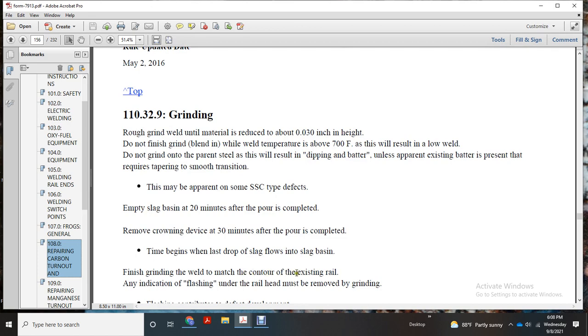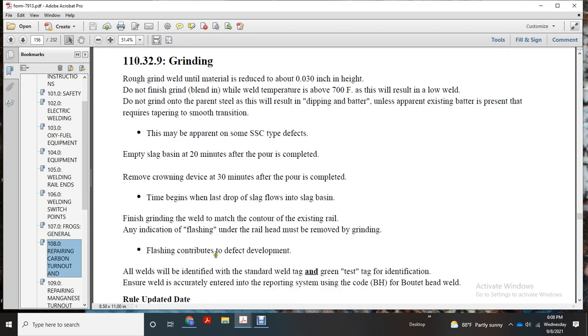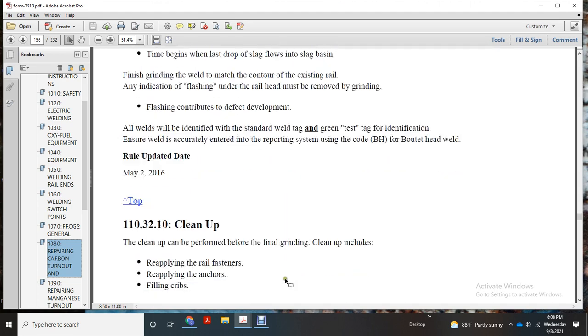Finish grind the weld to match the contour of the existing rail. Any indication of flashing under the railhead must be removed by grinding, as flash can contribute to defect development. All welds are identified with the standard welding tag and green test tag for identification. Ensure the welds are accurately entered in the reporting system using the code BH for the Boutet head weld.